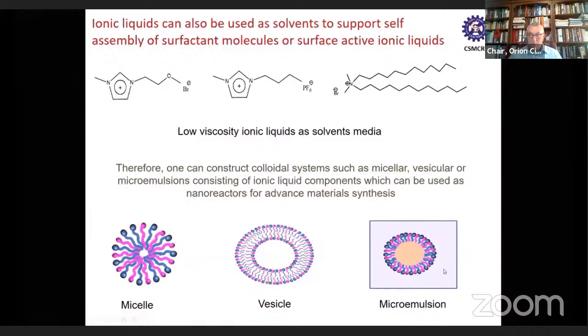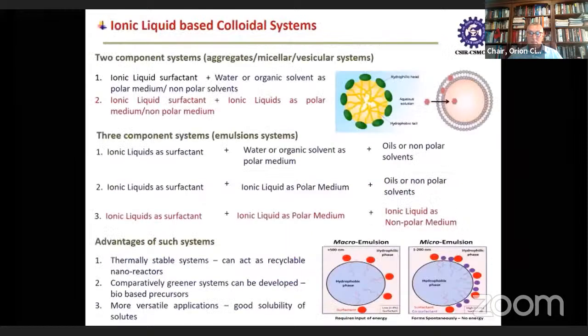So we are interested in producing these ionic liquid based colloidal solutions and using them in the synthesis of nanomaterials, particularly metal organic frameworks. If you look at different categories of ionic liquid based colloidal systems, they can be two component systems where ionic liquid is surfactant and the other medium is either water or organic solvents. Then one can have a more robust system where ionic liquid is surfactant and ionic liquid is a polar or non-polar medium. So these micellar structures can be formed, and one can make colloidal solutions of 3-component systems wherein ionic liquids can act as surfactant, ionic liquid can act as polar medium, or ionic liquid as non-polar medium. So using all the 3 components, one can make very robust ionic liquid based colloidal solutions or microemulsions, which can be used as nanoreactors for the synthesis of different kinds of nanomaterials.